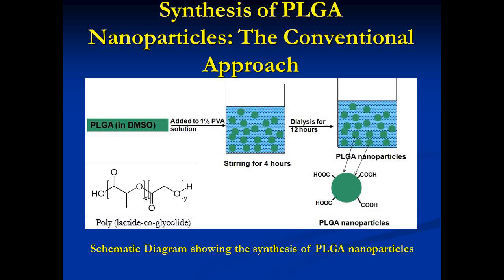This is a very common flow diagram of how to make nanoparticles. We used a very common biodegradable polymer, PLGA, polylactide-co-glycolide, and a surfactant, polyvinyl alcohol. It's simply a diffusion method to make the nanoparticles, where you do the dialysis and then lyophilize it to get a powdered form.